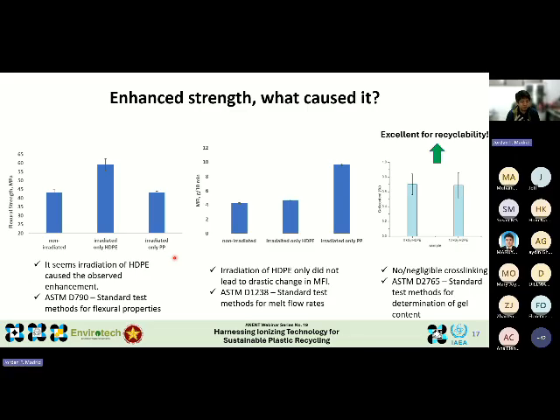So what we found was quite revealing: the improvement could be largely attributed to the effect on HDPE, the high density polyethylene. Interestingly, when HDPE is irradiated alone, we observed minimal changes in the melt flow index. The melt flow index basically tells us how flowing or how viscous the material is. So the higher the melt flow index, the less the resistance of the material to flow—it's more flowable, more fluid.